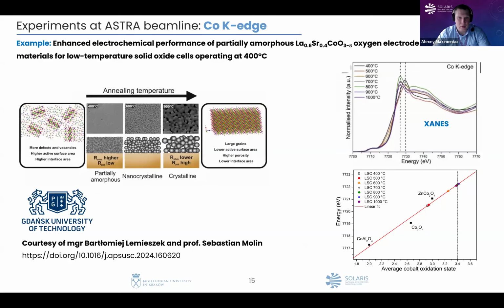Another experiment, I think, will be quite interesting for some of you, because I saw that in your program you have a lot of very interesting presentations about perovskites. Here is a perovskite which is used for low temperature solid oxide cells, and researchers from Gdańsk University annealed this perovskite at different temperatures and investigated how the crystal structure and the local structure of these samples change depending on the annealing temperature, and we helped the researchers to investigate it. At first we did XAS analysis, and XAS is very sensitive to the local structure of the absorber. It means that we could understand what kind of ligands are connected to our absorber and what the geometry of these ligands is.